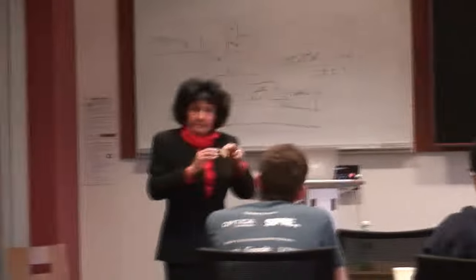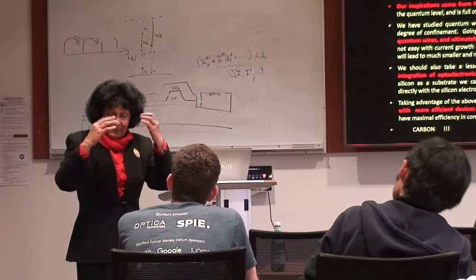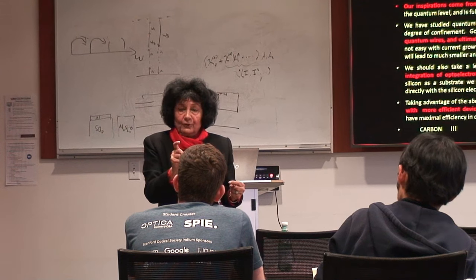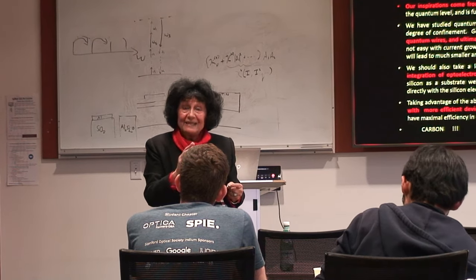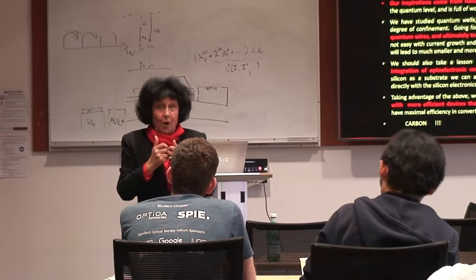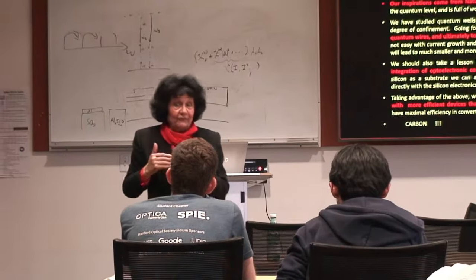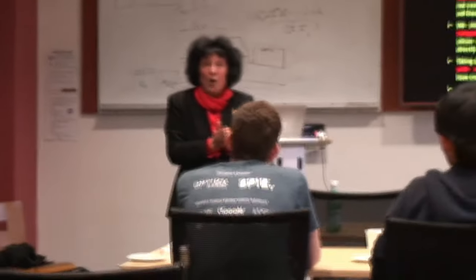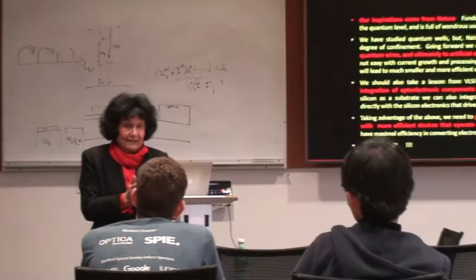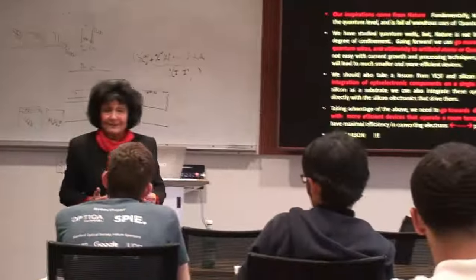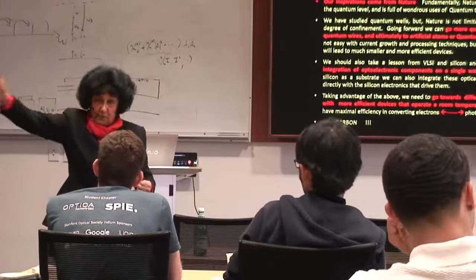First of all, you have to know that we do a lot of the physics understanding behind that. So what we do, first of all, we try to have the structure to make the quantum efficiency, it means the wall plug efficiency, the power that you are giving and the power that is coming out, to be as high as possible. So one of the beauties of the wide bandgap semiconductors is that you can manage to have very high internal quantum efficiency. And after that is the technology that is coming. If you put the heat sink, as an example, if you have aluminum nitride, or you put the copper, or you put the diamond, you can see that with the diamond, you can have 3 times more power to come out without killing the laser.